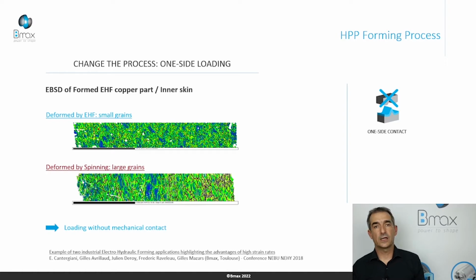In this example, it's a cavity in copper for the CERN. We perform a microstructure analysis to check the size of the grain and to verify the material property. Due to compressive stress in the material and no contact on the inner skin of this product, we have better material properties with EHF compared with mechanical spinning. Just for information, the cavity formed by EHF obtains the best result in the world in terms of performance for the CERN applications.